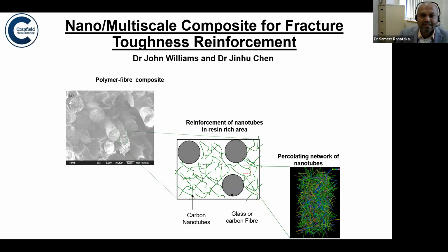But the problem with this material is that the glue which binds these fibers together is not as strong as carbon fibers. So whenever there is failure of this material, it usually happens within the glue. Okay. So how can we avoid failure? The way to avoid failure is to make this glue, or epoxy or polyester resin, which is used as glue, stronger. So how can you make glue stronger? We disperse graphene or carbon nanotubes within this resin. So the resin properties will also be increased. So this is one example. This is a cross section of this composite. These are carbon fiber or glass fiber, and the region between them is basically epoxy or polyester resin. Now that resin is mixed with carbon nanotubes or graphene.